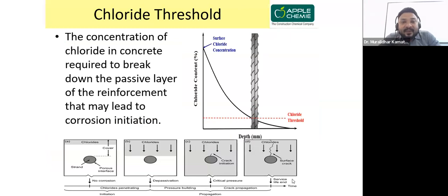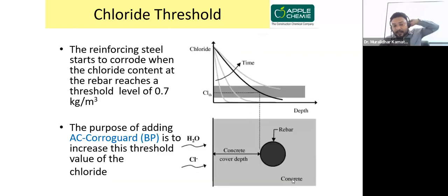Then there is the chloride threshold. The chloride threshold is the point at which corrosion initiation starts. After that point you can't have more chloride in your concrete. The purpose of adding AC-Corroguard here is to increase this threshold of your concrete. So why are we adding this bipolar corrosion inhibitor? Generally the threshold value is 0.7 kg per meter cube of concrete. Above that the chloride percentage cannot be tolerated.